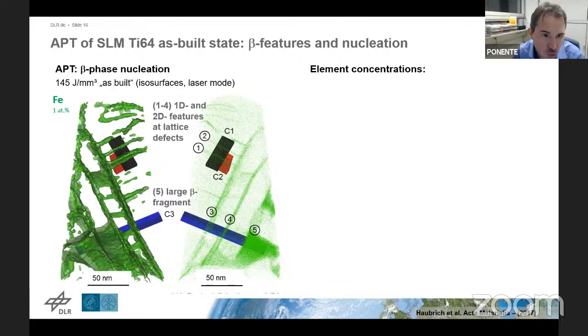Here is shown the distribution of the iron in one of those samples. Iron is another beta stabilizer. It's very sensitive in terms of the location of the beta phase. And you see on the left-hand side these elongated structures that correspond to the typical films. It's the exact same sample that I've shown with the vanadium a second before. So this is the film-like beta phase in the as-built state, but it also shows very fine elongated precursors growing from that, for instance here, or a larger particle down here at the bottom.